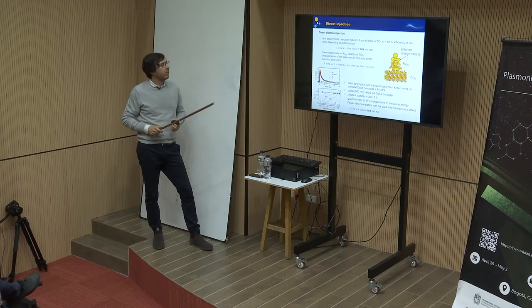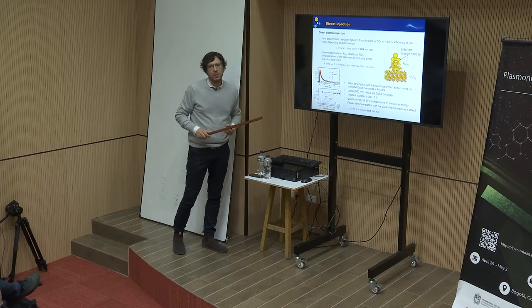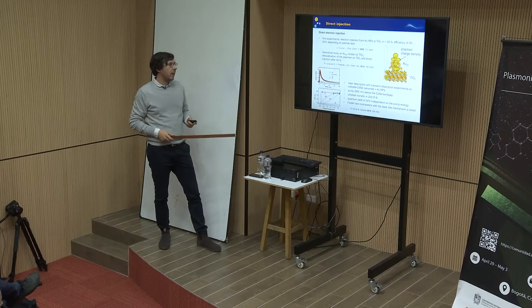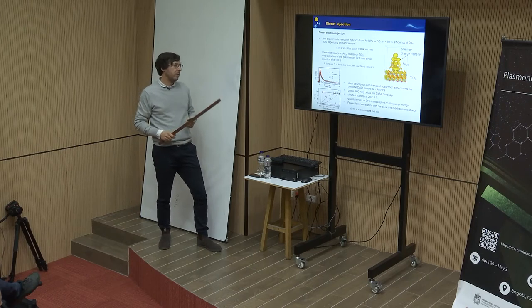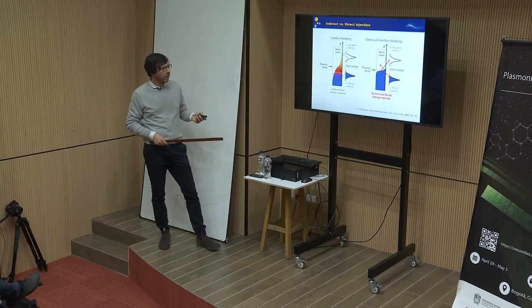through ultrafast pump-probe spectroscopy, where they see the creation of these states in gold-cadmium selenide nanorods. And they calculated a quantum efficiency of 24% for this process.